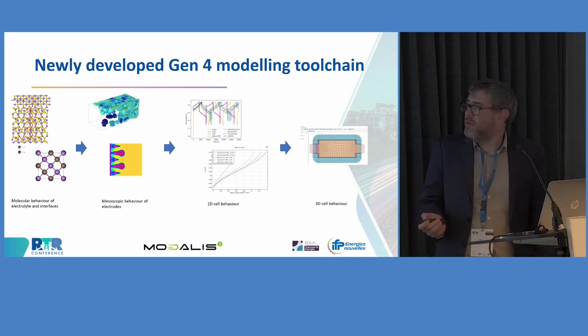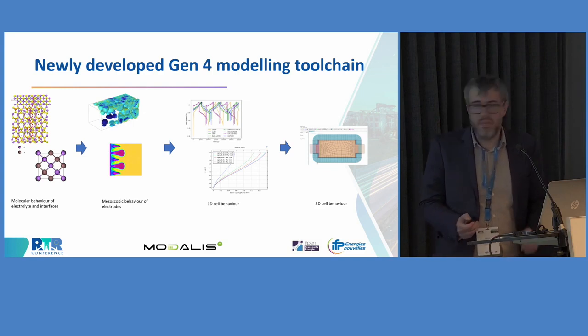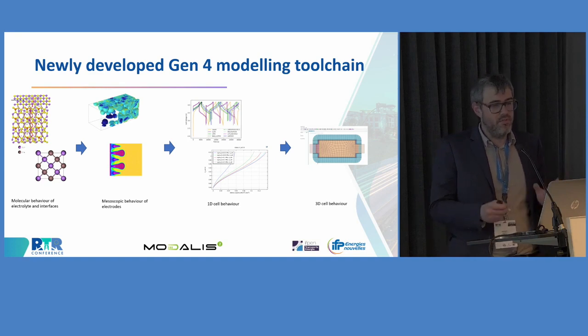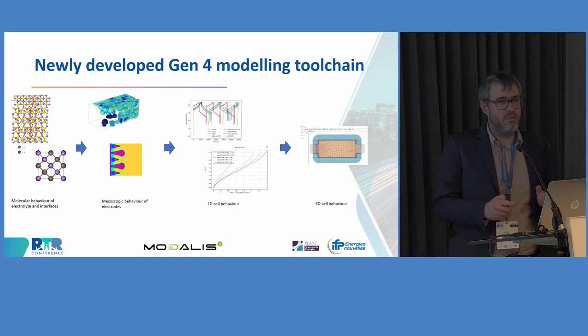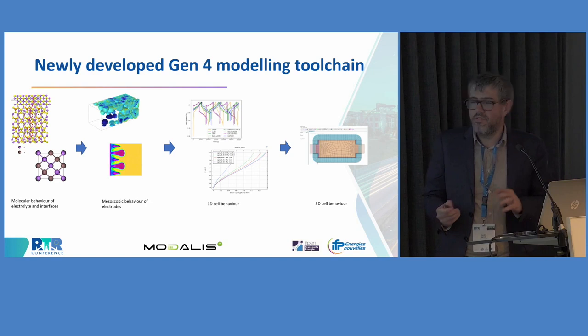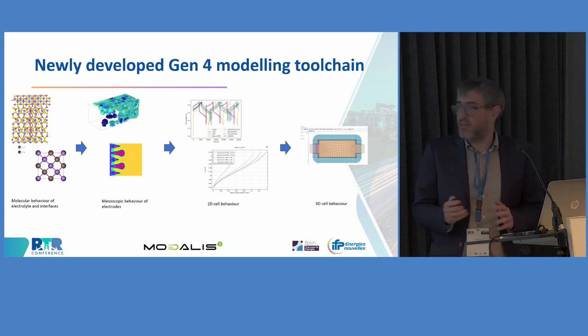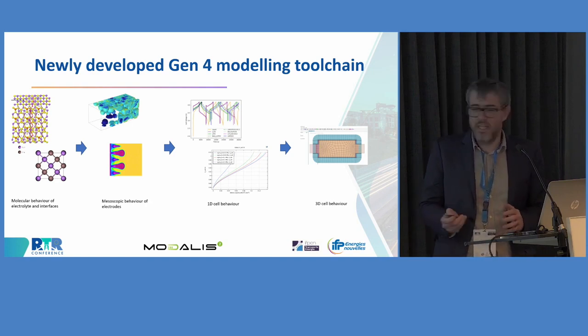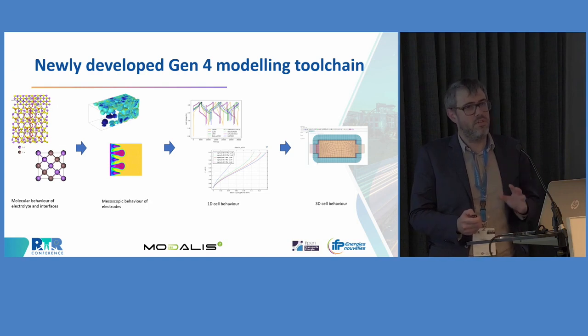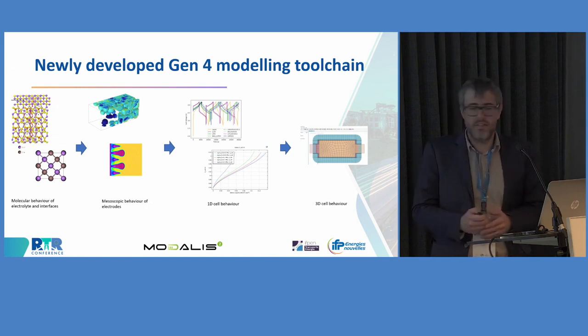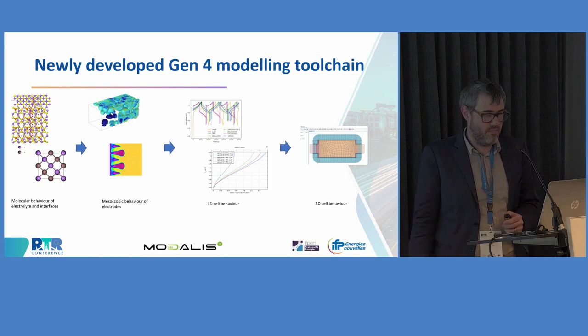Then we switched to mesoscopic behavior in order to understand the behavior of electrodes. On one side, the NMC solid electrolyte behavior with the positive solid electrolyte interface, and at the negative solid electrolyte interface, with specifically phase field modeling in order to understand dendritic growth at the negative interface.